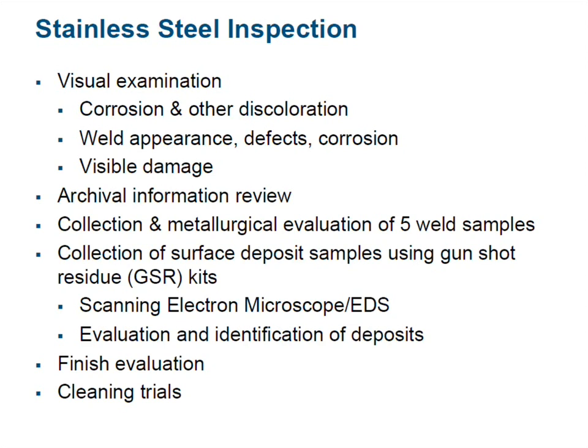For stainless steel, this stainless steel inspection, we were looking at a number of different things. First of all, a visual inspection. Is there corrosion or other discoloration? The appearance of the welds, including possible defects and any corrosion around them. Corrosion patterns can tell you a great deal, as can the appearance of a weld, and other visible damage. We went through archival information, and we got 5 weld samples to evaluate.